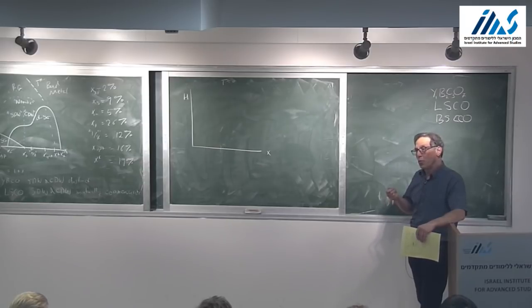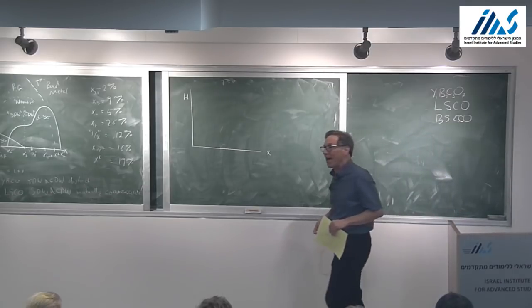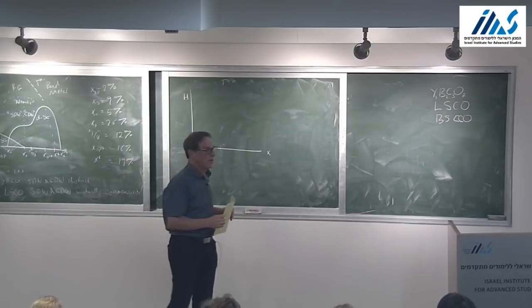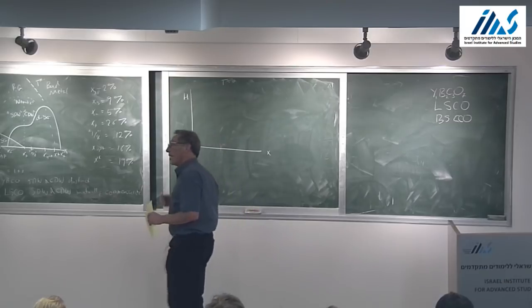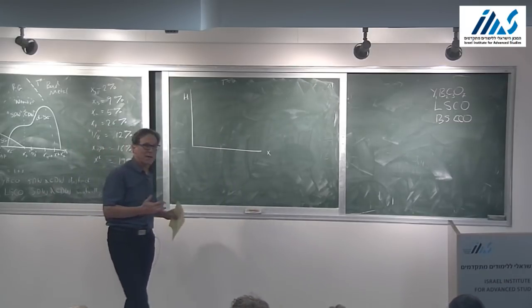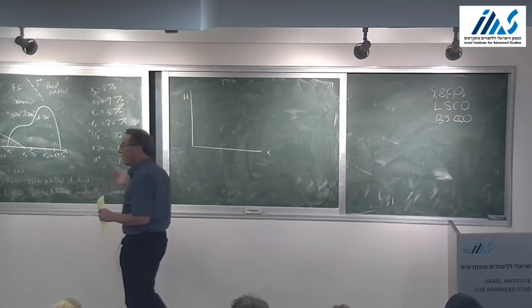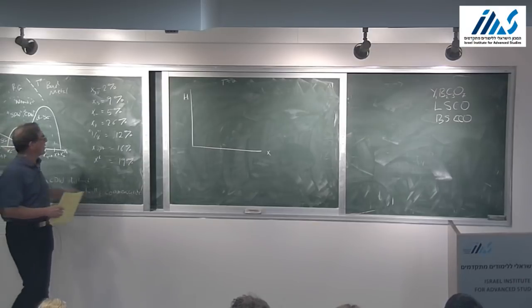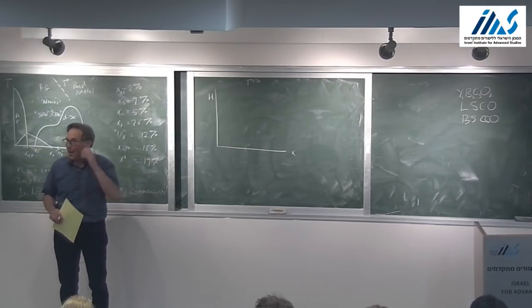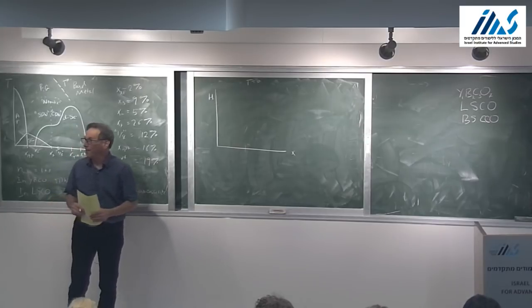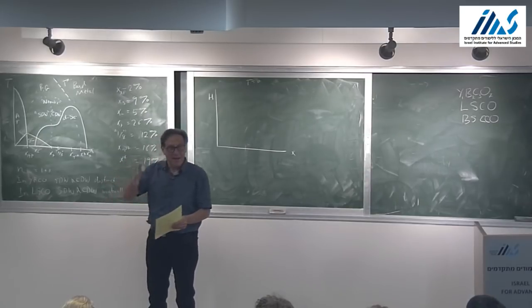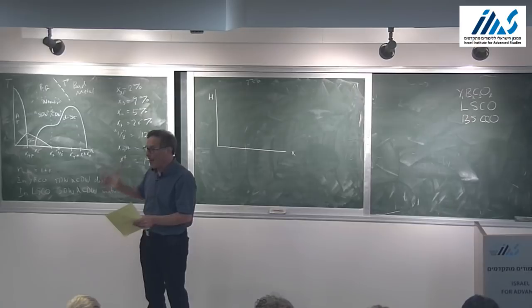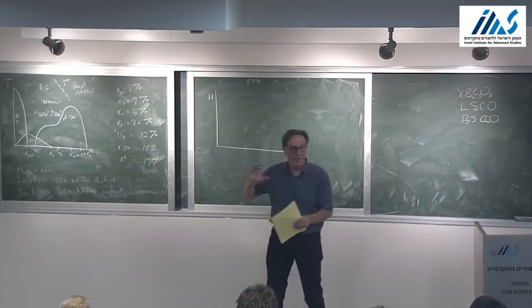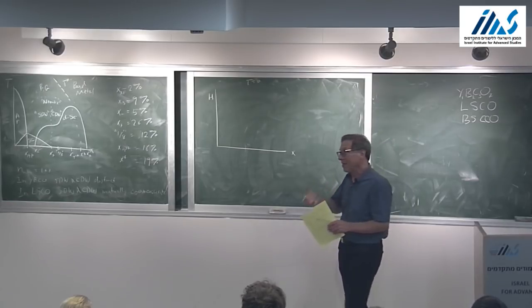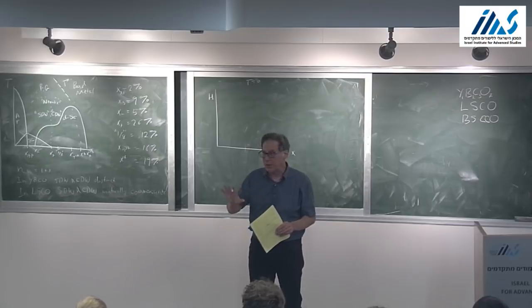And the one exception to that is superconductivity. So superconductivity, of course, couples very strongly to magnetic fields, and above some critical field is suppressed. And so the idea here was, let's turn on a high magnetic field, high enough to suppress superconductivity, but at least we'll imagine in our minds that other than killing superconductivity, it's not doing a lot. And so it's giving us some idea of what the phase diagram would be with superconductivity turned off. Now, that's of course a lie. It's telling us what the phase diagram is with magnetic field high enough that it's killed superconductivity. The idea of superconductivity turned off is a mean field notion.